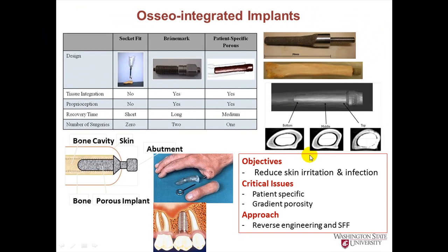What we've shown in this work is that because we can work from CT scan images, we can tailor-make the size of the implant depending on the pore cavity, as we placed in dog cadaver bone. We worked with 20 dog cadaver bones, did design modifications and variations, and finally showed that we can significantly enhance mechanical locking by tailor-making these implants.